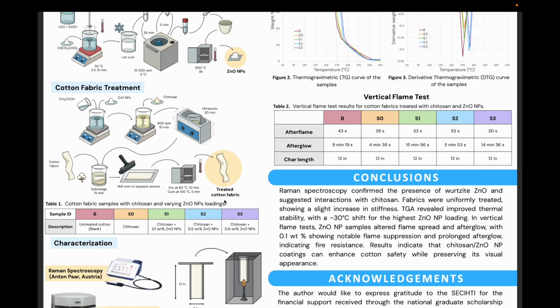Then 1 gram of chitosan was slowly added at 900 revolutions per minute for 10 minutes. The mixture was homogenized in an ultrasonic bath for 30 minutes, and cotton fabric samples were then submerged in the mixture for 50 minutes. Then it was laid flat over wax paper and passed through a roller to remove excess liquid. The fabric was dried at 80 degrees Celsius for 10 minutes and cured at 100 degrees Celsius for 5 minutes.